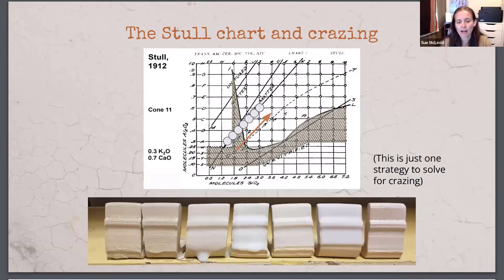So a lot of people tend to think that they might have a glaze that's in the crazing region, but it's not crazing, and they want to fix it. But if it's not crazing, then it's perfectly fine. So just keep that in mind. The crazing region was based on Stull's experiment, and this region changes depending on the clay body you're using. But the general pattern stays the same. So if you're over here in crazing, you can get out of crazing by going this way. If you're down here, you can get out by going up. And so that's kind of the way to look at that.